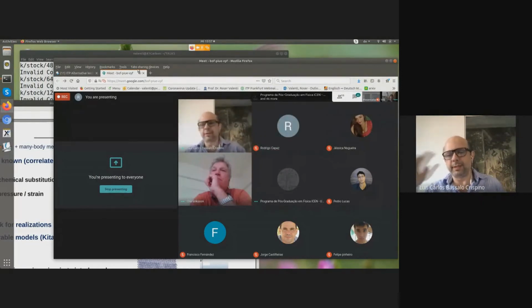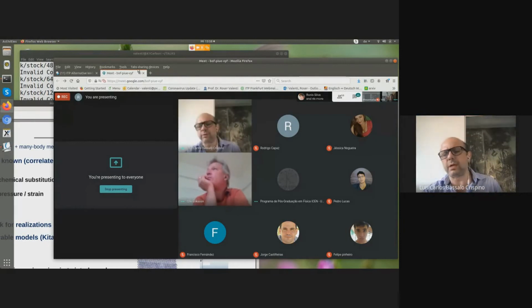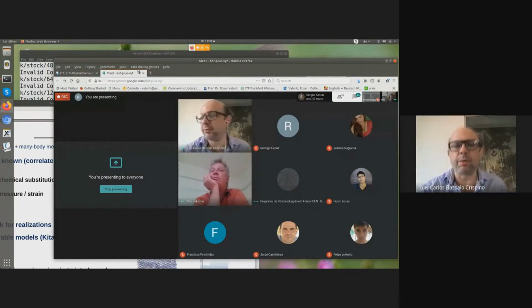Professor Van Sérgio from our university, Pará University, first, thanks you for the excellent and very didactic webinar. And he is mentioning that a recent work from himself and collaborators, called superconducting and pseudo-gap transition temperatures in high TC cuprates, and the TC dependence on pressure, has been published, and they derived an analytical universal expression for the critical temperature and the pseudo gap in the cuprate superconductors as a function of the doping. He mentioned that and asked if you can comment on that.